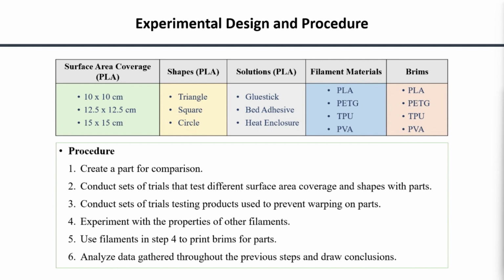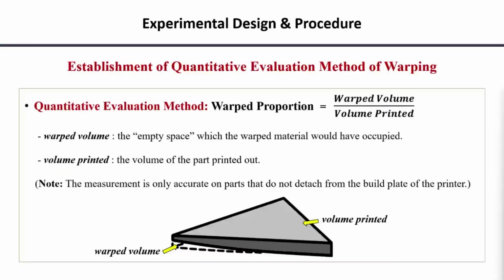On experimental design and procedure, this chart and these steps are all the necessary information. After conducting the experiments and gathering the data, I could finally analyze it. The formula used during this experiment was warped proportion is equal to warped volume over volume printed. Elaborating on these values, warped volume is the empty space which the warped material would have occupied, and volume printed is the volume of the part printed out. Now, this measurement is only accurate on parts that did not detach from the build plate of the printer, and using it, the following table was able to be completed.